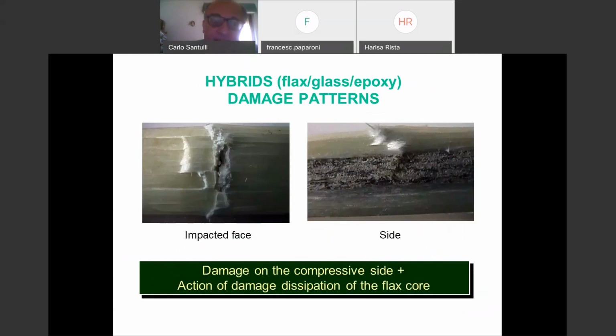This is a typical hybrid. This is flax plus epoxy. This is the hybrid I was talking about in the previous slide. And you have the impacted face. You have the side, and you have damage which progresses and goes till the end, but with less evidence. The glass fiber is not able to completely stop damage. So you have two skins made of glass epoxy and a core made of flax epoxy, and you have a kind of damage dissipation. The flax core provides some damage dissipation, but not sufficient to stop real damage.